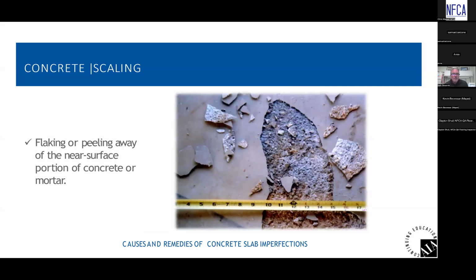Scaling is another term when you lose the entire surface of the concrete. This is very common when air-entrained concrete is used in an interior application where they steel trowel it. So they typically entrain air into concrete for exterior applications in freezing environments so that there ends up being voids in the concrete so that when that concrete gets saturated in the wintertime when water can freeze, the water goes into these voids created by the air bubbles and expands and doesn't affect the concrete.